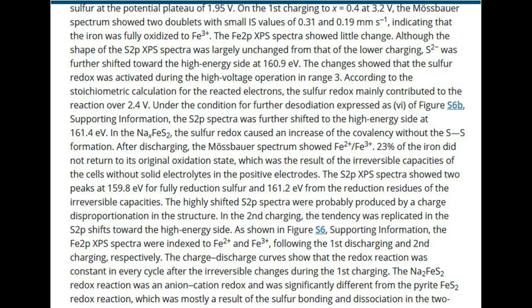According to the stoichiometric calculation for the reacted electrons, the sulfur redox mainly contributed to the reaction over 2.4 V. Under the condition for further desodiation, expressed as 6 of figure S6b, supporting information, the S2p spectra was further shifted to the high energy side at 161.4 eV. In the NaxFeS2, the sulfur redox caused an increase of the covalency without the S-S formation.